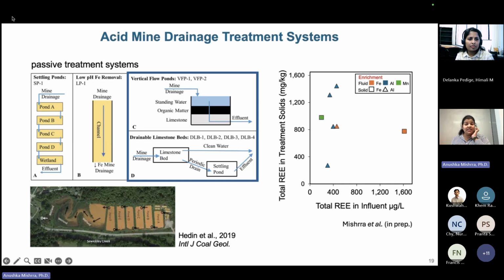So up to 1600 micrograms per liter, which is very high. And when you look at the same sites and the treatment solids, now you see more REs in the solids, which is very interesting because a site that we would probably not look at because it has low REs could be valuable in terms of the treatment solids that are there, because they may have now enriched amounts of REs in them. So this is very interesting.